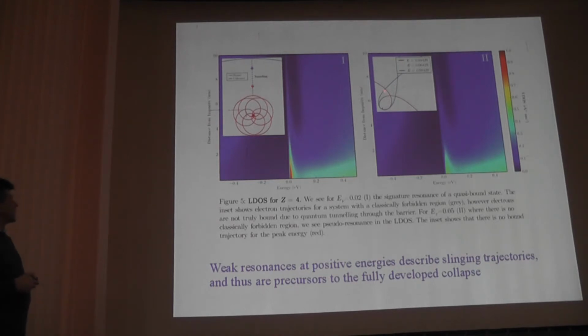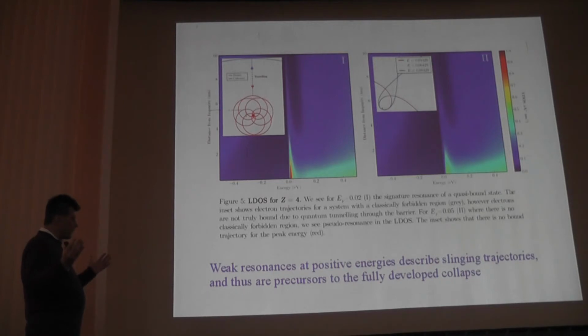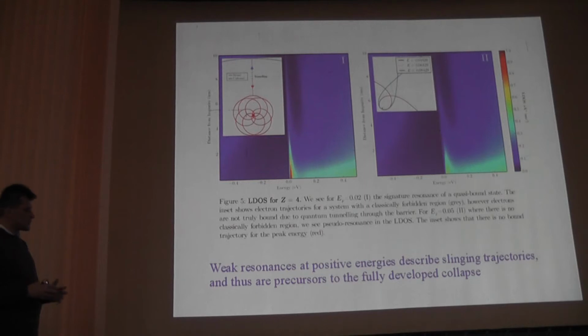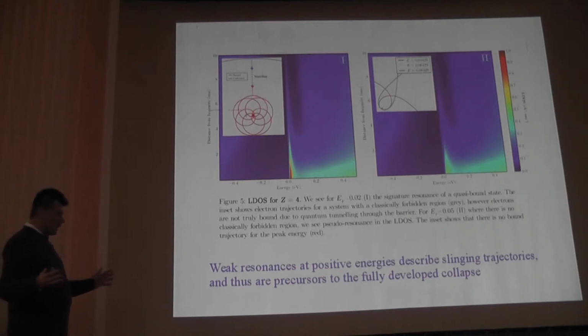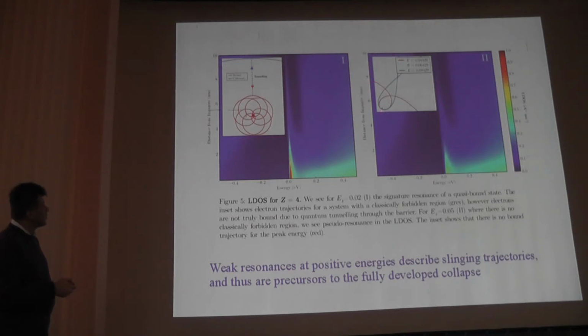We also tried to investigate the resonance state at positive energies, and the explanation basically was that after you do the self-consistent solution, that changes the form of the potential. The potential becomes screened, it's suppressed at large distances, and you can work out the details of this. You can look at the trajectories in this potential. You can notice that these positive energy resonances come from trajectories like this. So here is this spiral describing the true collapsing state, very sharp resonant peak, and here is a semiclassical trajectory representing states in this broad peak at positive energies. You can notice that this trajectory only makes one full turn, but otherwise it's not qualitatively different from this one. So that's a kind of precursor to the collapse. So it's not in contradiction to the theory.